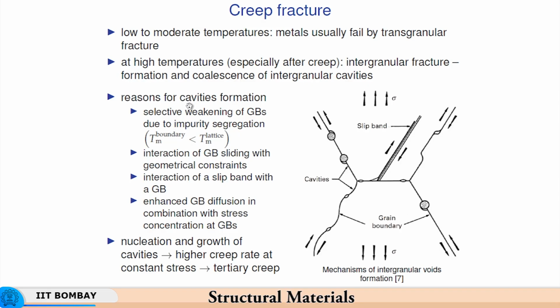So, the reason why cavity formation takes place is because of selective weakening of the grain boundaries, because the temperature is well above the equicohesive temperature, and equicohesive temperature is the temperature at which the strength of the grain and strength of the grain boundary both become equal. So, initially the grain is relatively softer, meaning the grain boundaries are stronger at room temperature. So, the deformation takes place inside the grain.